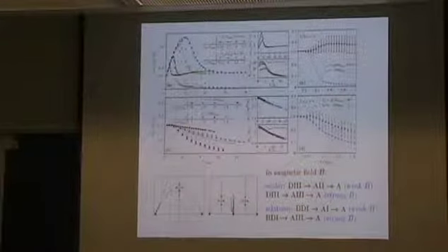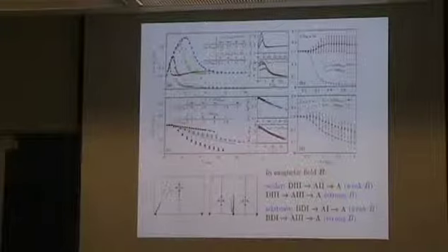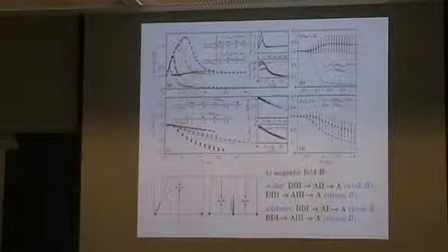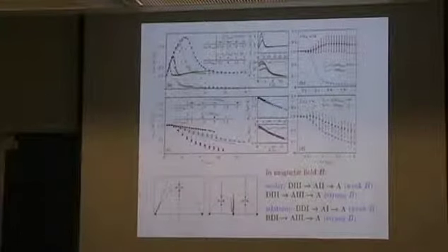So what kind of model is this? The model is graphene with rare scatterers, which are characterized by some scattering length. And here, the scatterers do not mix valleys. So we characterize scatterers by a scattering matrix. And there are two situations. In one, they completely scatter between valleys. In another case, they scatter only within each valley. And the time-reversal symmetry breaking comes from magnetic field.